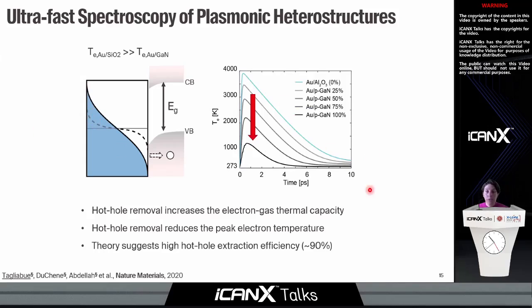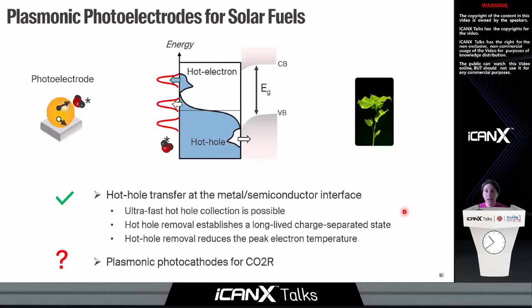So indeed, we have performed theoretical calculations also to demonstrate this, and we have observed that as we increase the fraction of removed hot holes, the peak electron temperature decreases, and from comparison with the experiments, we could estimate an extraction efficiency of close to 90% in our system.